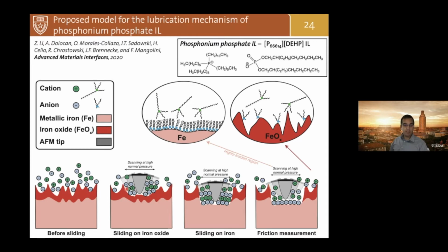As the scanning tip slides at high pressure, we start organizing the ions through lateral confinement, something that I'm not going to talk about today. If we slide at extremely high loads, we go through the oxide, which results in a difference in the way in which the phosphate ions bind to the surface. In the case of iron oxide, you have only monodentate configuration, whereas in the case of metallic iron, you have bidentate configuration, which, thanks to the surface being extremely smooth and the lateral confinement of the AFM tip, the ions basically maximize the interaction energy, reduce the configurational entropy, and form this densely packed boundary layer that is helpful in reducing friction.